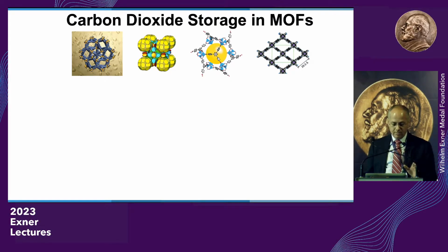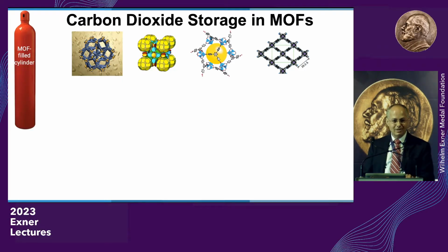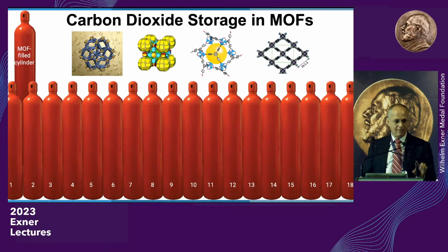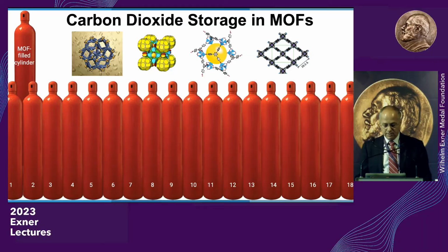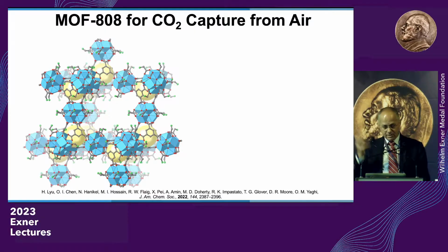And I just want to summarize and say that in a MOF-filled cylinder like this, like you would have in your laboratory, we can store 18 times the amount of CO2, even though the MOF occupies volume in the tank or in the cylinder. So that means that the MOF acts to compact or bring CO2 molecules into the pores and compact them within a smaller space. And so that tells you what the capacity could look like eventually.